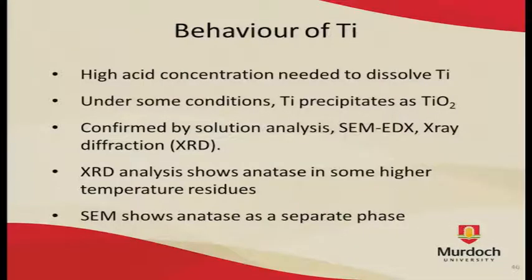Titanium extraction was a lot more dependent on the acid concentration. Titanium dioxide is fairly insoluble, it's fairly stable in solution as well, and was observed to precipitate. This was confirmed in a few different ways. I've not shown the X-ray diffraction patterns up here, but in quite a few of the higher temperature residues, there are a few fairly prominent anatase peaks, anatase being a form of titanium dioxide, the variant that forms when titanium precipitates from sulfate solutions. In chloride solutions, it tends to form rutile, a different crystal structure.